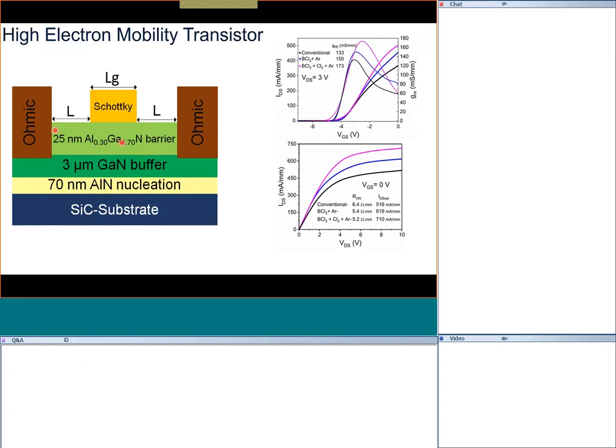The fundamental operation is similar to a MOSFET: we apply a bias between source and drain ohmics, apply a gate bias at the Schottky contact, and the AlGaN barrier layer roughly serves as the oxide. Applying a gate bias modulates the channel at the AlGaN/GaN interface — that is the transistor action. One important advantage: you can have the entire structure undoped. The carriers come from surface states, so you don't need to dope the structure at all to have carriers in the channel.